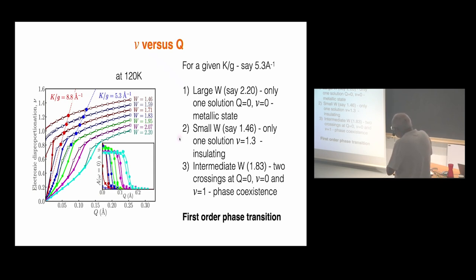And this is the result that Oleg Peil and co-workers found. This is the electronic disproportionation, so nu or n as a function of Q. And you find the curves which have been obtained. Let's follow, for instance, this curve, K over g equals 5.3 angstrom minus 1. Now you see that for this curve, if you have a large bandwidth, 2.2, there is only one solution to this equation, which is 0.